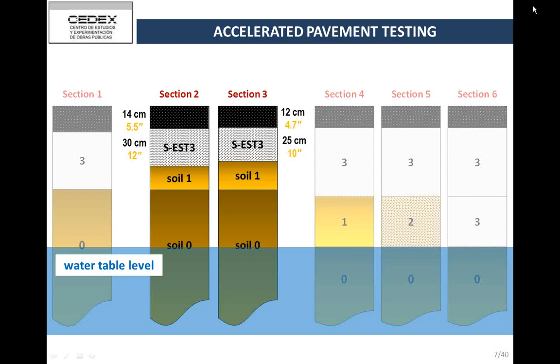And because of that, that translates also into loss of bonding, because it's like you would have the asphalt on a very thin layer of sand, and underneath the sand you have the soil cement. And according to your experience, what is the typical, the maximum depth of that crumbled material? It's going to be less than 2 centimeters. Less than 2 centimeters. Yes. Okay. If you go deeper, the material would be sound, would be very strong.